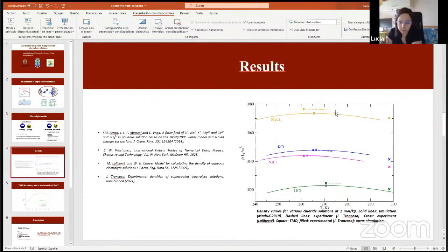And here I show the results, and I want to clarify that it is very difficult to do experiments in the supercooled region of water because there are certain nucleation phenomena that often make the sample freeze before being able to measure it. And so here we have the results from Jacobo Troncoso at the University of Vigo, who has recently been able to measure electrolyte solutions at low temperatures. And the squares are the maximum of density, the temperature of the maximum. And the crosses are other experimental results at ambient temperature from Laliberté.